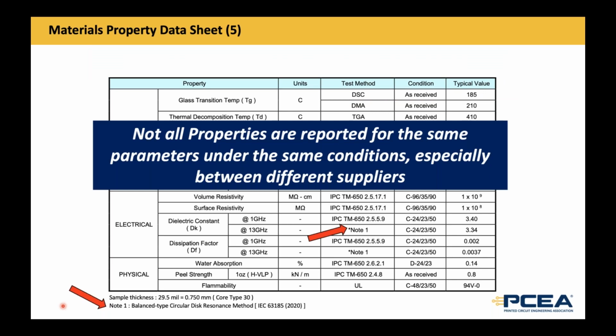Now, the other thing is that not all properties for the same parameters are measured under the same conditions, not only between different suppliers, but often between different products from the same supplier. In this slide, you see that the dielectric constant is reported at 2 different frequencies. If I showed you 5 of our other products, that 1 gigahertz number is probably always reported because it's a typical IPC value with an IPC test method. But the 13 gigahertz number is not typical. Some people might report 10 gigahertz. Some people might report 16 gigahertz, depending on their test method.